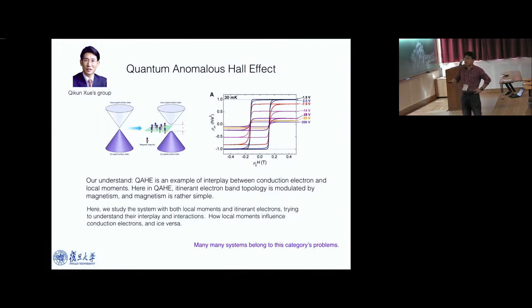On the surface of a three-dimensional topological insulator, there is a time-reversal symmetry protected Dirac cone, right? So now if you introduce dopant, like magnetic dopant, like chromium, the system of the local moment of the chromium forms a ferromagnetic order. Form a ferromagnetic order. So ferromagnetism enters and breaks time-reversal symmetry, and the Dirac cone of the surface Dirac cone will be gapped, right? So the combination of trivial simple Dirac electron coupled with ferromagnetism, you get a gapped spectrum.